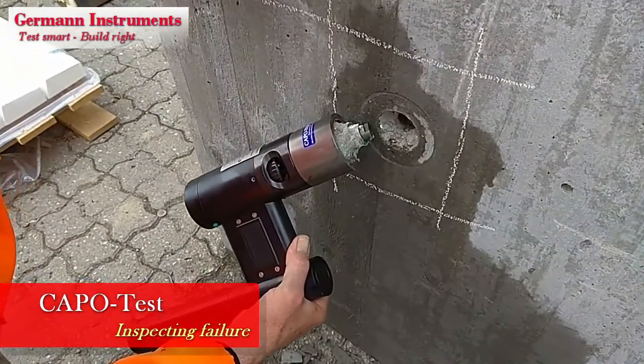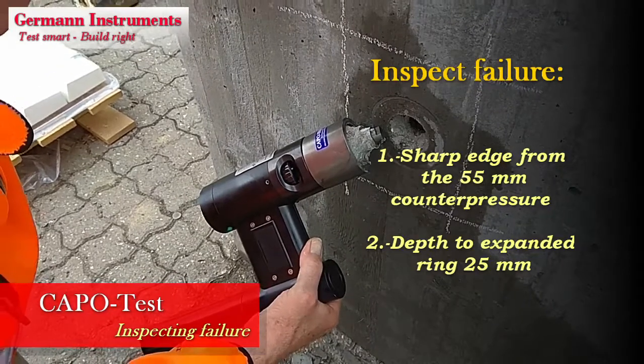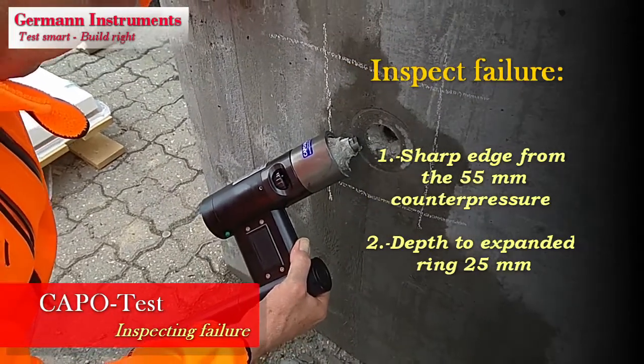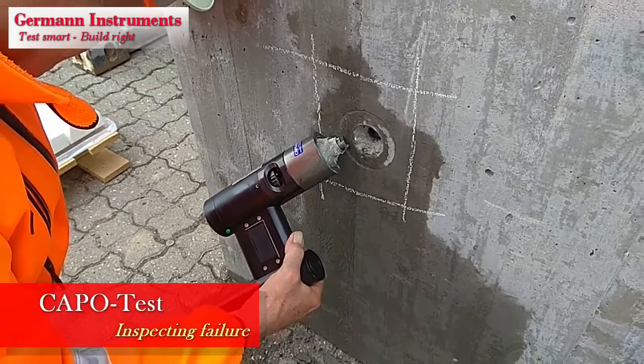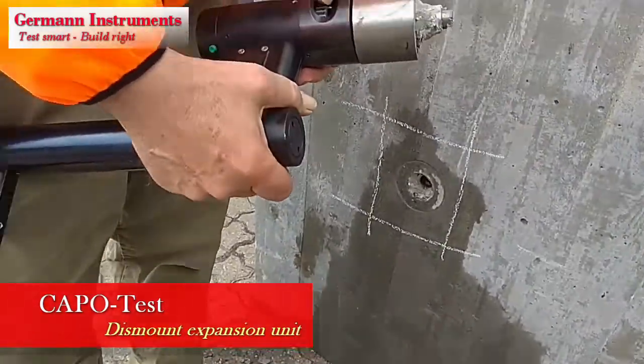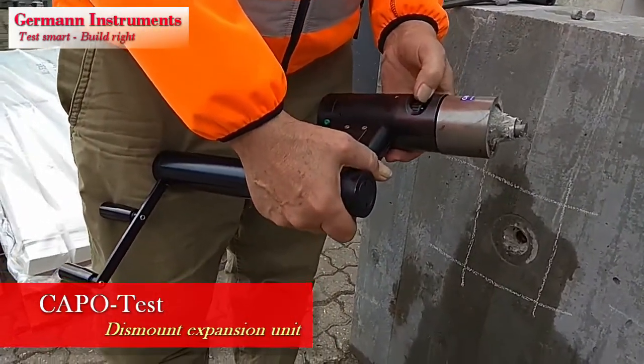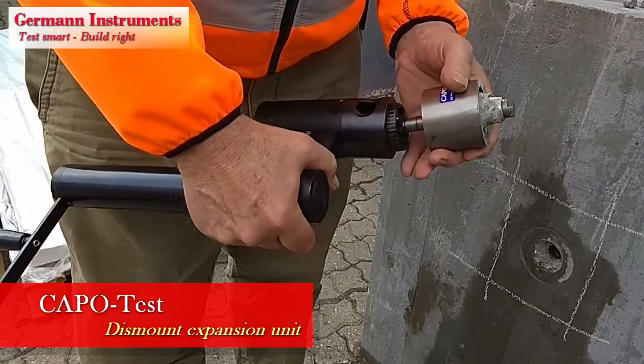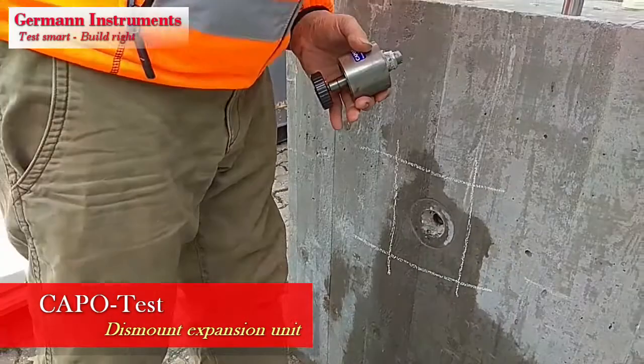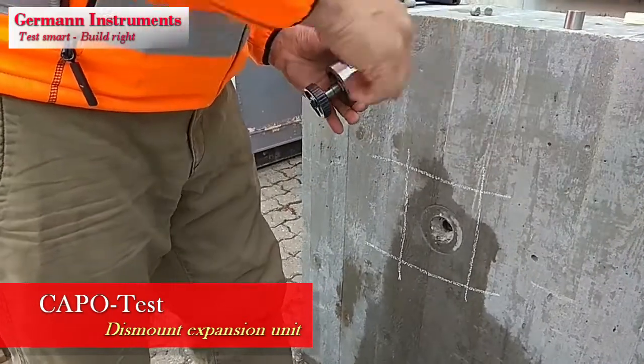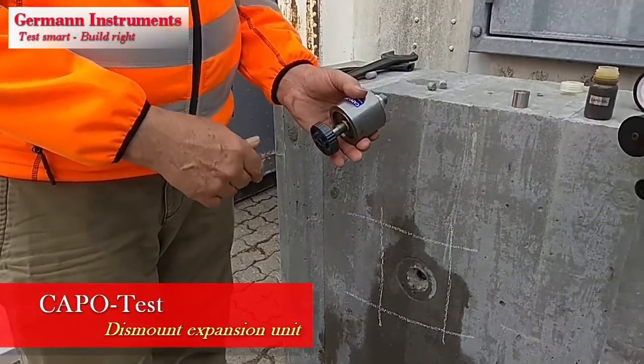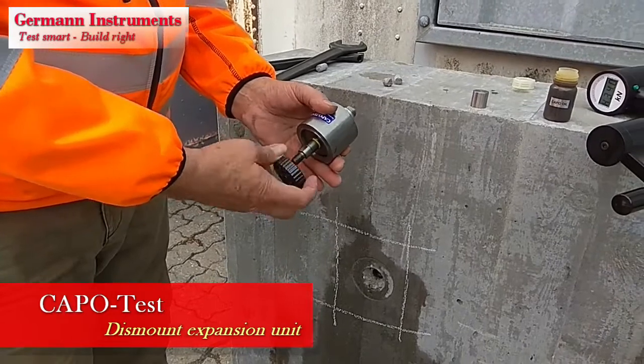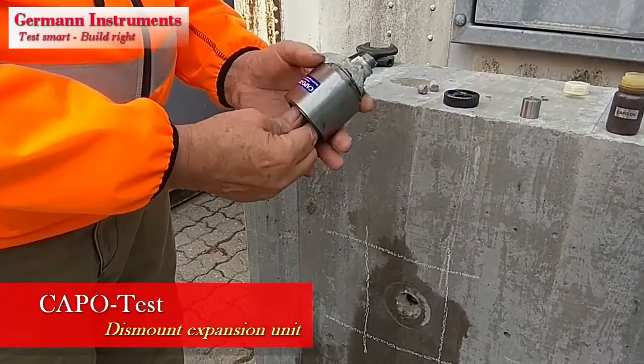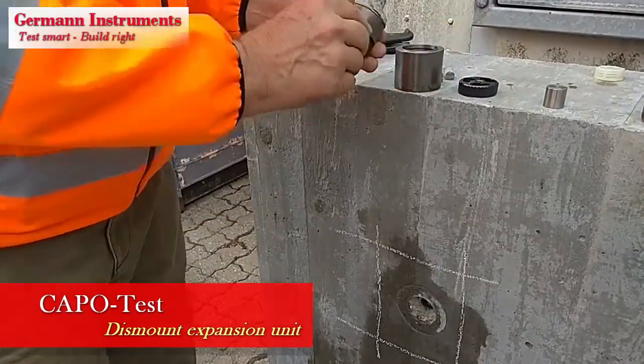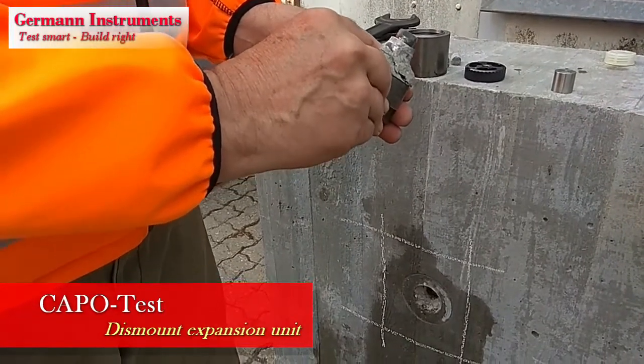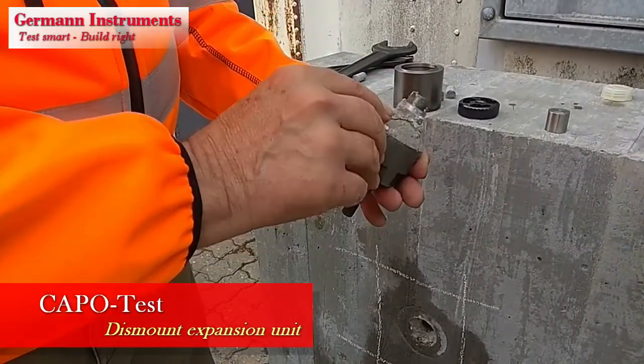A properly performed CAPO-Test has, as with the lock test, to show a sharp edge on the concrete surface from the inner 55 mm counterpressure ring, and the depth to the expanded insert must be 25 mm. Uncouple the coupling from the instrument, then unthread the coupling from the base pull bolt and remove the counterpressure. Note the cracks in the extracted cone. They are formed in the softening regime, where the parallel cracking in the compression strut is sliced between the outer ring edge and the inner counterpressure ring.